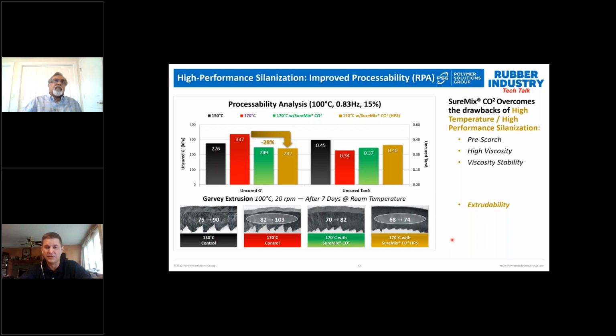And you also see the drop in the uncured tangent delta going from 150 to 170, and what that tells you is it's going to be a rougher extrusion, which you see below. And then you see the increase in the uncured tangent delta as we add SureMix and reduce the silane. Now the garvey die extrusions in this case show a lot. Going from 150 to 170 degrees C, you see the compound roughness. You see those numbers above, those are actually the Mooney viscosities.